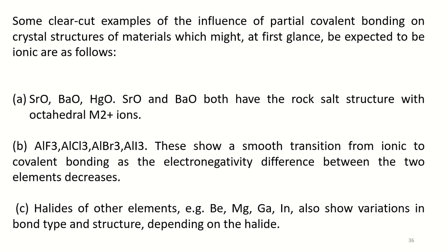Hybridization of the 6s and one 6p orbital gives rise to 2 linear sp hybrid orbitals, each of which forms a normal electron pair covalent bond by overlapping with an orbital on oxygen. Hence, mercury has a coordination number of 2 in HgO.